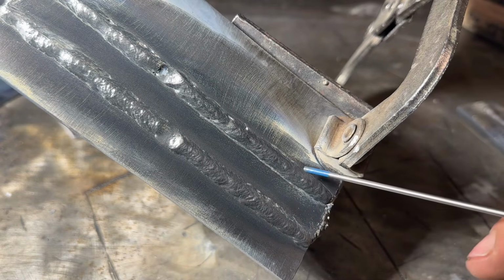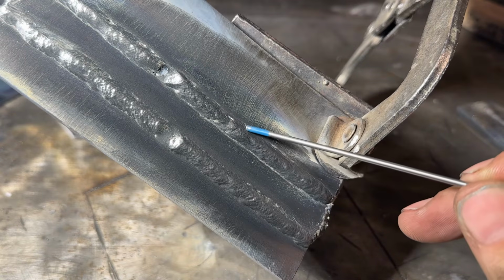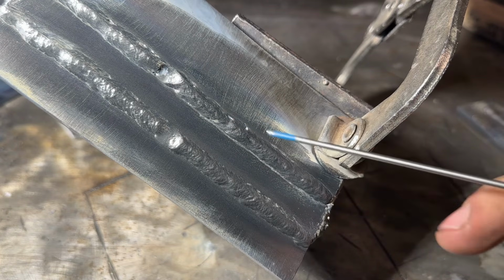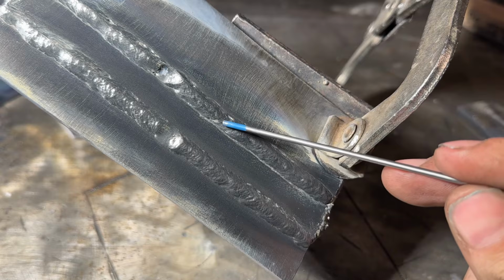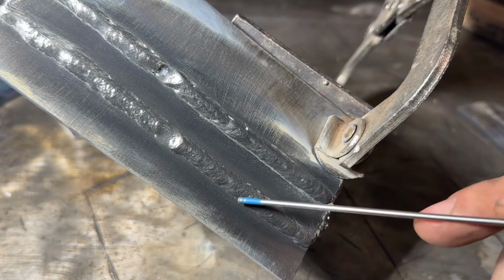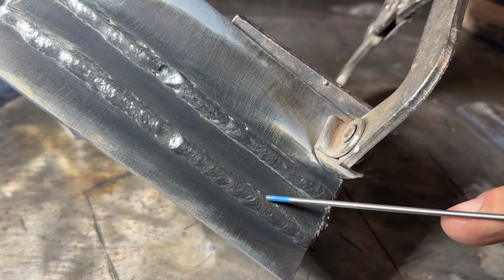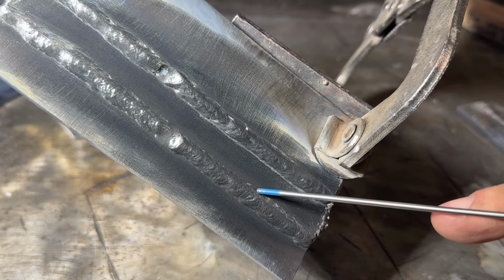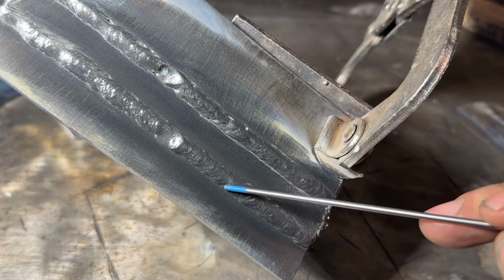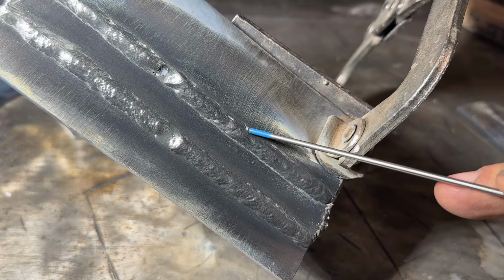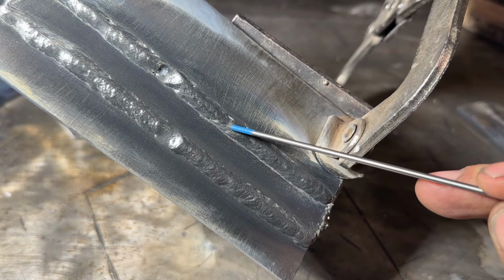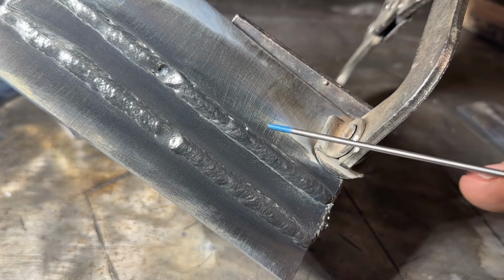So this is, I mean, pretty much perfect up until where I kind of moved a little bit. And you probably saw maybe something changed in the arc footage at this point. This has a little bit of undercut on the side or underfill. I think it's just from moving too fast. That could also be, again, travel speed increase and then it doesn't fill.